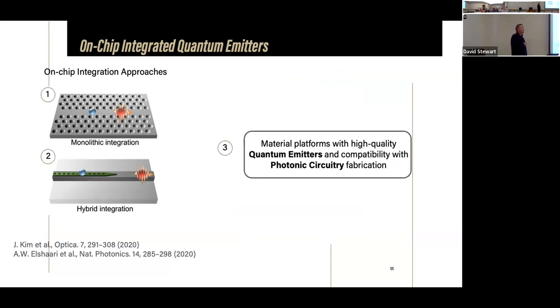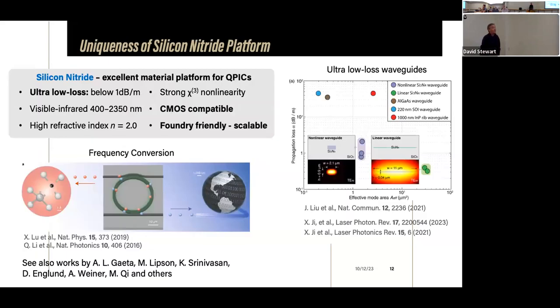So the bottom line is, it would be really great to have a material platform with high quality inherent quantum emitters, with a material which is CMOS compatible and foundry friendly. And that brings me to silicon nitride. The simple reason why it's becoming more attractive, even compared to silicon, is just losses. It's all about losses. I put here 1 dB per meter, but I just came from the Frontiers in Optics conference. Shalaev reports something like 0.02 dB per meter in silicon nitride. So it's really quite spectacularly low losses, which is very, very important for this quantum photonic circuitry.